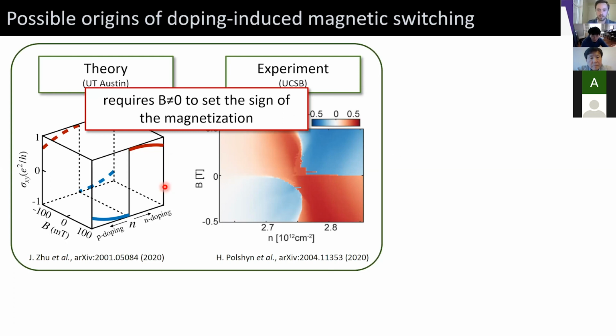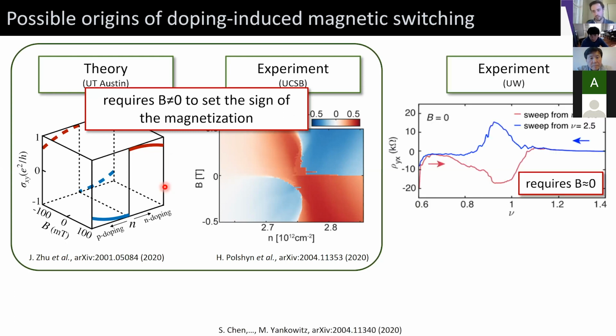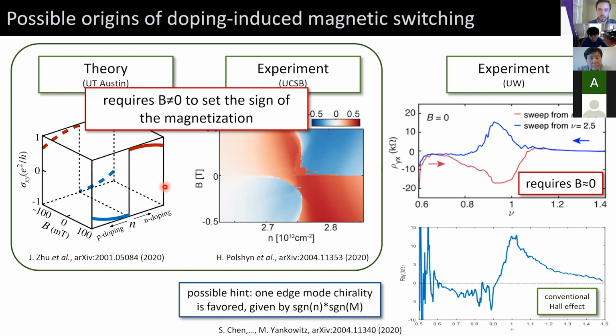Whereas in contrast, what we find is that it only works around zero magnetic field. Even a few millitesla suppresses the effect. So this really should violate some sort of intrinsic symmetry of the system, and there's no explicit time reversal symmetry breaking. So there's no reason why it should necessarily choose to be up or down deterministically. And so that's really quite a curious phenomenon.